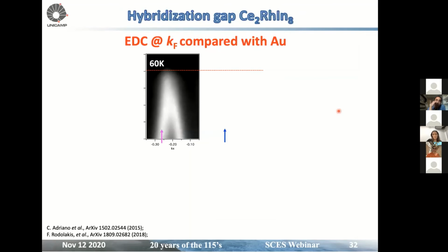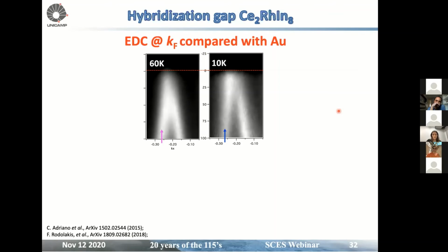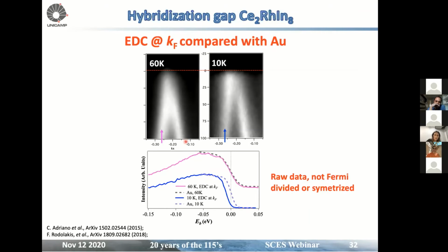So talking about the gap now, the hybridization gap. We compare high temperature with low temperature, and from maps, I'm telling you, it's impossible to say anything. But then we took EDCs, energy distribution curves, at kF, for that linear band here, and what we did, we compared that with gold at the same conditions, same energy, which is very important to determine the gap, as we are on a synchrotron, so the energy that you set on your monochromator is not always the energy you get after your optics.